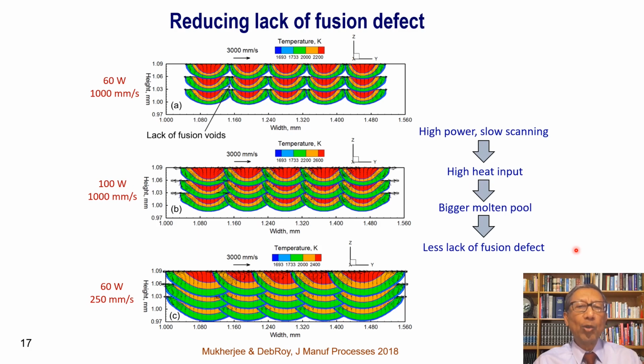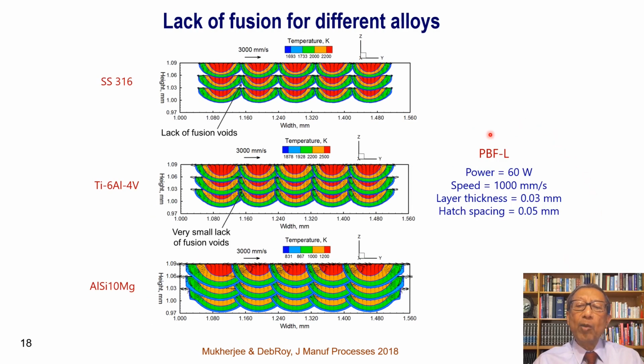That means if the power is low and scanning speed is fast, then the fusion zone would be smaller in size and there is likely to be less overlap between adjacent hatches and between layers. And for a given set of process variables like it is given here, the thermophysical properties of the alloys determine the size of the fusion zone. And this is what we see here. In case of stainless steel 316, the fusion zone size is smaller than aluminum silicon 10 magnesium alloy.